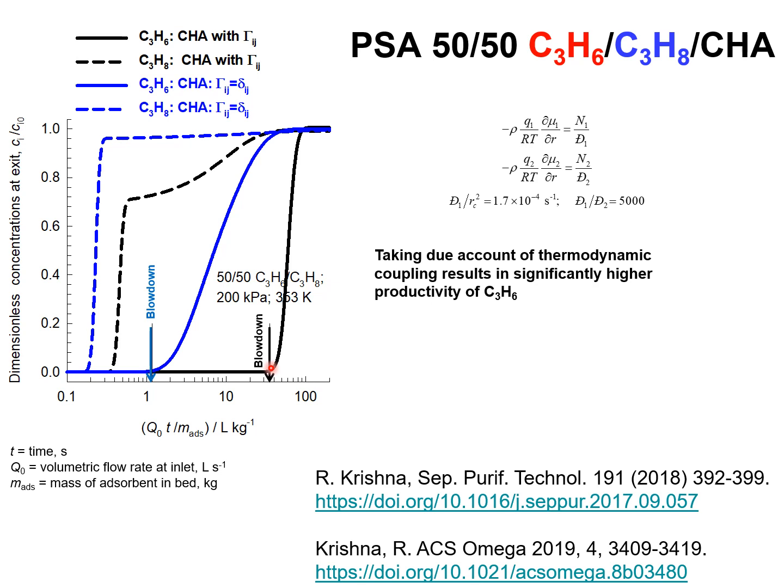This is because of the large overshoot in the propene loading that was demonstrated in earlier slides. The attainment of supra-equilibrium component loadings within the particle accounts for larger uptake in the fixed bed adsorber.